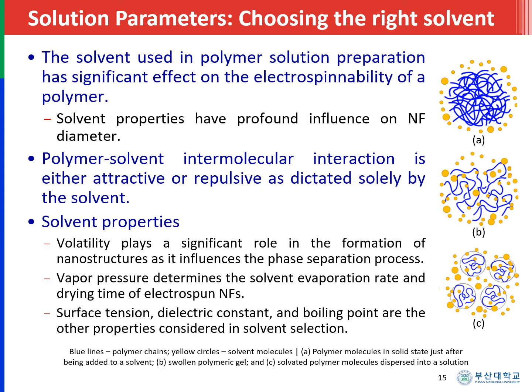Choosing the right solvent is very important in electrospinning. The solvent used in polymer solution preparation has a significant effect on the electrospinability of a polymer. Solvent properties have great influence on nanofiber diameter. If the polymer and the solvent molecules have good intermolecular interaction, then expect that you will be able to produce quality nanofibers in electrospinning. You have to take note that the intermolecular interaction could either be attractive or repulsive, and it is actually the solvent which dictates this interaction. The solvent properties that you have to consider are volatility, vapor pressure, surface tension, dielectric constant, and boiling point.